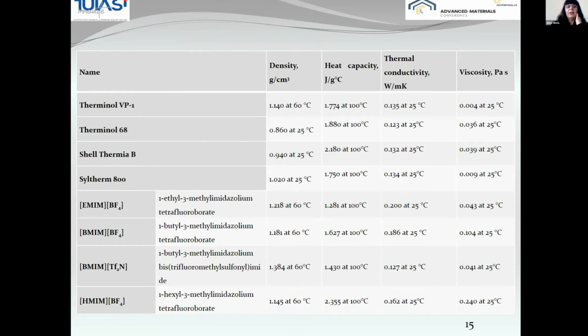Here in this slide, I tried to outline a little bit some basic properties of some regular oils used at high temperatures and several ionic liquids in terms of density, heat capacity, thermal conductivity, and viscosity. You can see here very clearly that ionic liquids are more viscous than other fluids, but also the thermal conductivity is in a very good range.